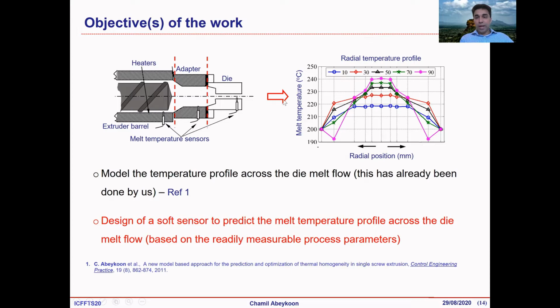But as the screw speed goes up, you could see 10, 30, 50, 70 and 90 RPM. Now at 90 RPM, the maximum in the middle is 240, and the lowest, somewhere close to the die wall, is around 192. So the variations are as big as 50 degrees. That is a big issue.